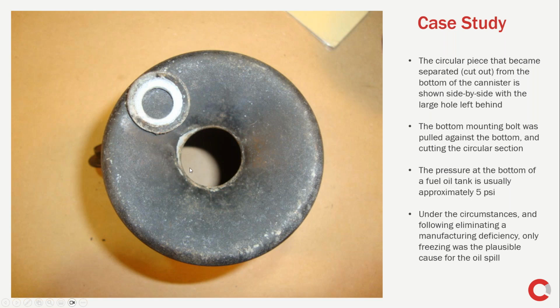Typically, the pressure at the bottom of a fuel oil tank is around 5 psi. This amount of pressure isn't enough to cause the damage that we see here, which is cutting out the bottom and even bending the material. So we can infer from that that an abnormal event occurred. And given the circumstances, and after ruling out manufacturing deficiencies, freezing really emerged as the most plausible cause for this failure.